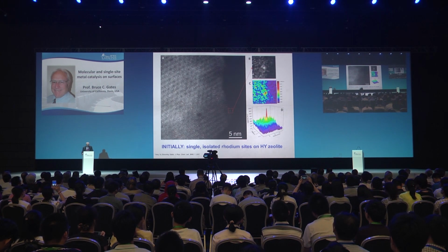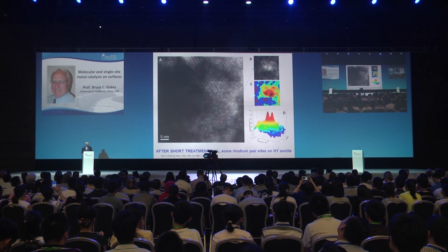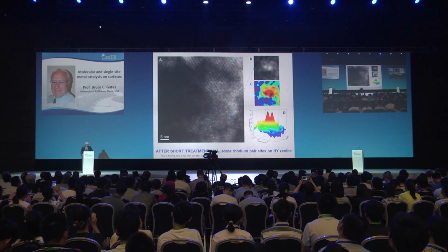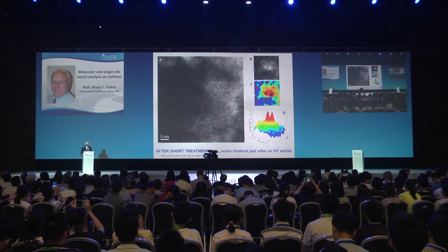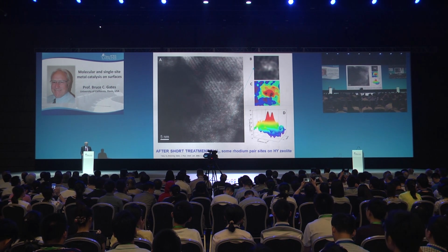Then we treat it in hydrogen just for a little bit, just for minutes, and we start seeing pair sites show up. Here's an intensity analysis showing rhodium pairs, rhodium dimers.